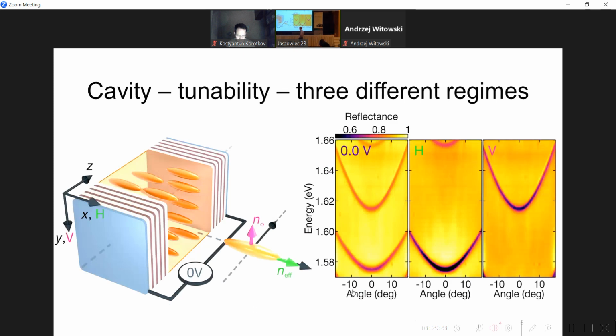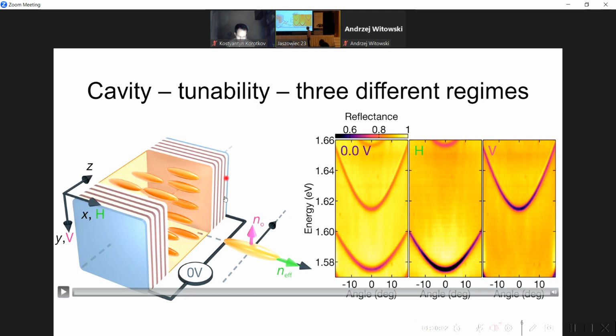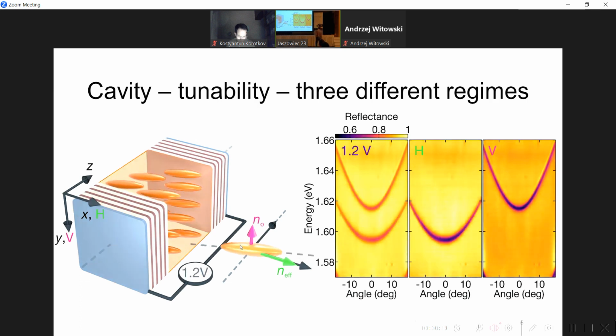In addition, in our case we have birefringent material inside the cavity, which means we have different mode energy because for horizontal and vertical mode we have different refractive index. And if we apply external voltage to the ITO electrode, we can change the refractive index in the x direction and finally change the energy of the horizontal mode.